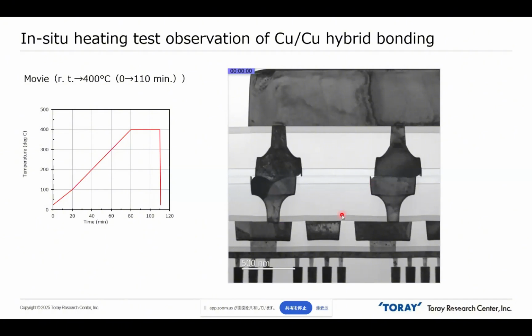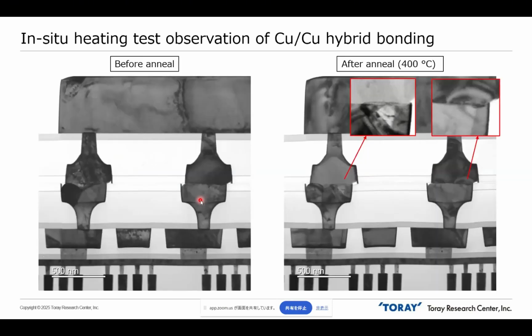So here we also prepared a cross-sectional thin lamellar specimen of the Cu-Cu hybrid bonding. In this case, we fabricated this cross-sectional sample from commercial devices. So this sample is already tightly bonded in the initial state. But as a test measurement, we applied heat to this thin lamellar specimen. After heating, it is not so easy to find a clear difference, but by checking this cross-sectional image carefully, we can find Cu diffusion from the lower part to the upper part, and from the upper to the lower.